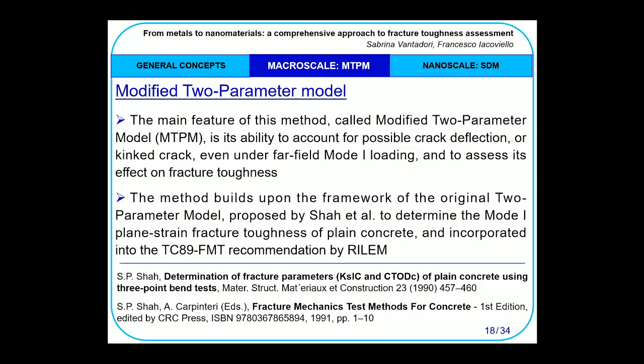Let's start the discussion with a proposed procedure for fracture toughness evaluation of quasi-brittle materials. The main feature of this method, called the modified two-parameter model, is its ability to account for possible crack deflection or kinked crack even under far-field mode 1 loading, and to assess its effect on fracture toughness. The method builds upon the framework of the original two-parameter model proposed by Shah et al. to determine the mode 1 plane strain fracture toughness of plain concrete and incorporate it into RILEM recommendation. Therefore, I will begin by outlining the main steps of the original method.